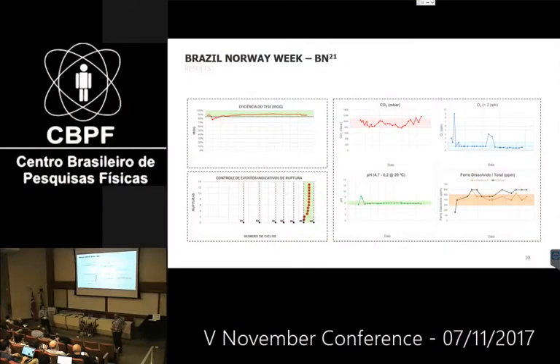In the beginning of the test, we have no iron content in the solution. The test was started with a new pipeline and with no corrosion on the armor wires. The solution was transferred to the pipe in deaerated condition and saturated with CO2. Besides that, we did this first measurement with very low contents of iron. During the next days, the iron content starts to increase up to saturation. After that, it stays saturated throughout the test.